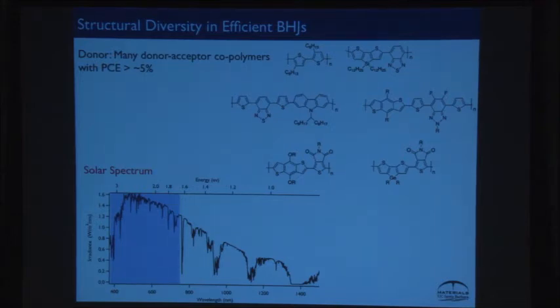Most of the efficient, what's called bulk heterojunction organic solar cells, which I'll define a bit in the next slide, have polymers in them. And they also have a fullerene molecule. So it's a mixture of two things. The structural diversity tends to come from the polymer side, and the fullerene tends to be relatively constant. Cells are efficient absorbers out to about 750, maybe 800. There's a lot of push to increase the absorption, to increase coverage of the solar spectrum. And that's where a lot of the scientific challenge is.